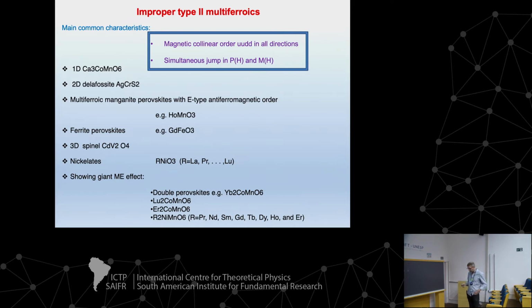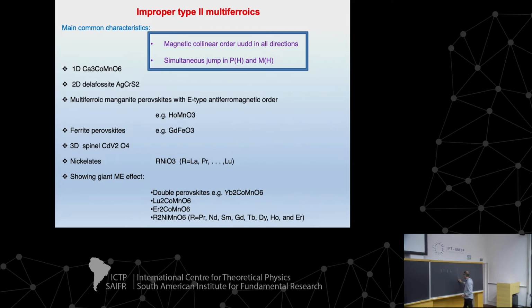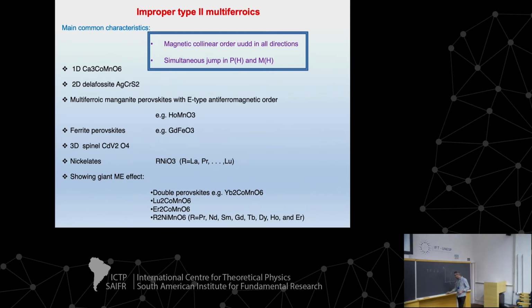The second issue is that there are simultaneous transitions. If you look at the magnetization as a function of the magnetic field, it is something like this. You have a jump of the magnetization at some critical magnetic field. This is nothing very strange. But at the same time, what happens in many of these materials is that the polarization goes to zero.